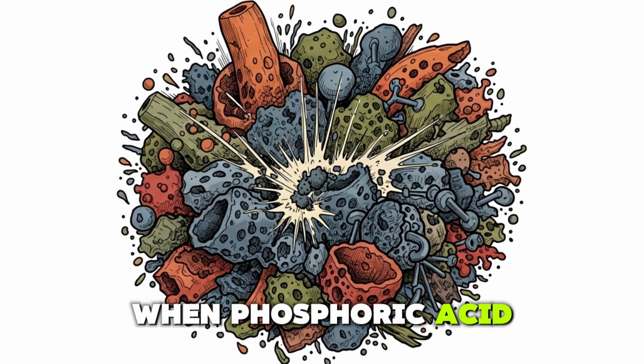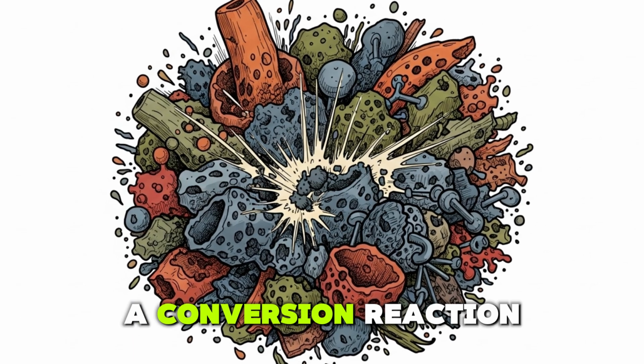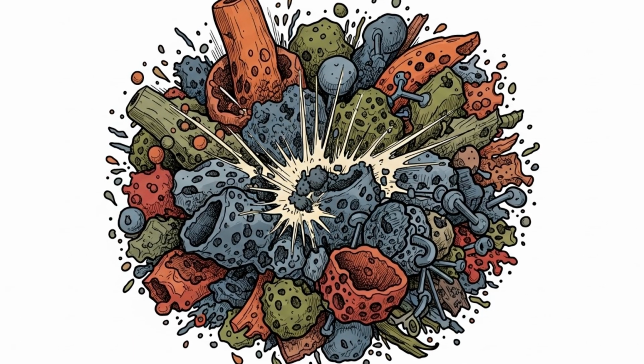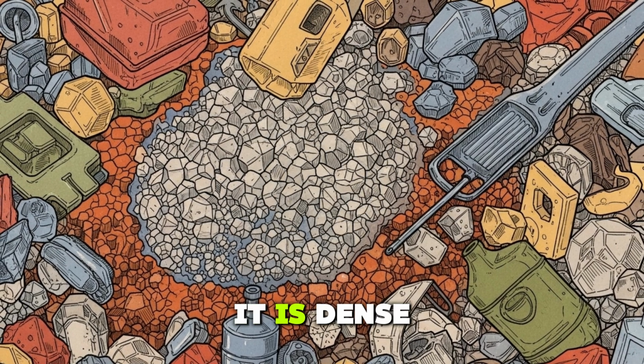When phosphoric acid is applied to this surface, a conversion reaction begins immediately. The hydrogen ions in the acid attack the iron oxide, and through a process of ionic exchange, the iron atoms are released from the oxide structure and recombine with phosphate ions to form ferric phosphate, a compound with fundamentally different physical properties. It is hard. It is dense.